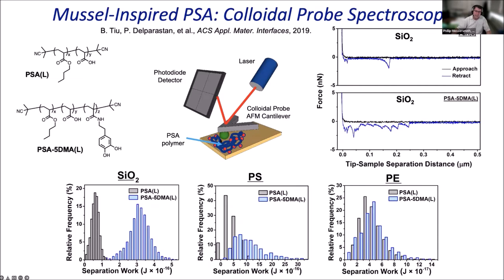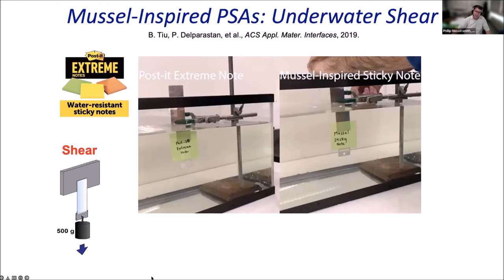And then we measured the strength of adhesion of a little particle of either glass or polystyrene or polyethylene to this polymer surface with and without the mussel inspiration. And you can see if you just add a few percent of that mussel inspiration underwater, you can increase the adhesion to glass several fold. It works a little better for polystyrene, and we still have a lot of work to do for polyethylene. So it really doesn't have much of an effect on polyethylene adhesion, but it does significantly increase the wet adhesion strength to oxide surfaces. And I'll just show a cute little video that we made of this.